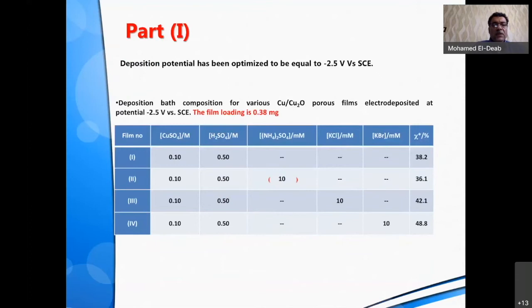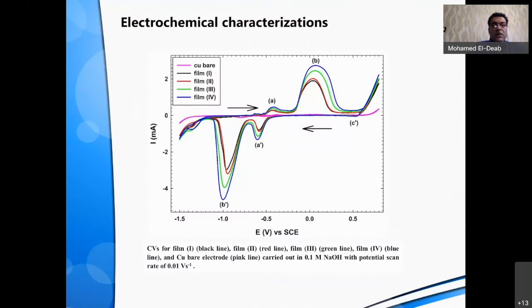effect of additives on the copper foam prepared from acidic copper sulfate. And here you can see this is a typical CV for different films prepared in presence of different additives. And you can see film number 4 in presence of bromide shows the highest peaks for the redox pattern for copper, which indicates a successful deposition of copper foam atop of the substrate.